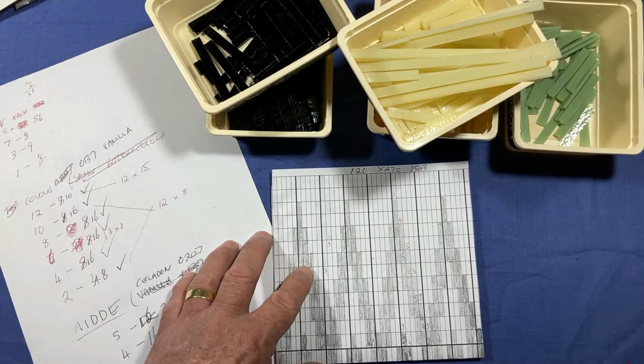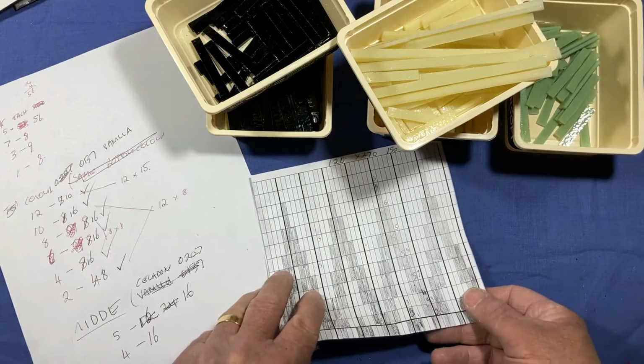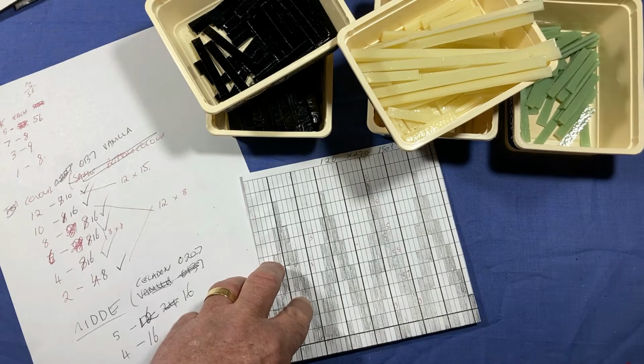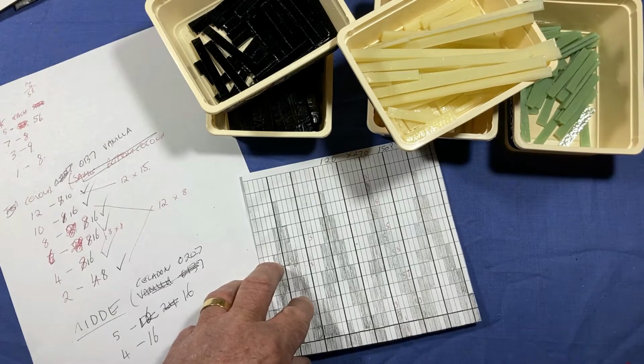But before I go into all that, just for those who haven't been on my channel before, all the glass that I use here is Bullseye COE 90. When I'm fusing, I generally fuse on thin fire paper. When I'm slumping, I slump into boron nitride. The firing schedule, which is in the description below, if you're using some other COE, you'll need to adjust it. And don't forget, every kiln can fire quite differently.